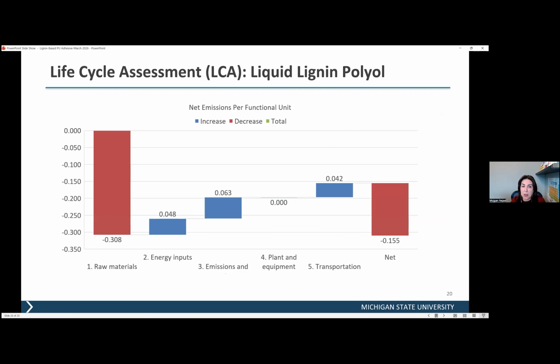We also hired an outside firm, and they did a life cycle assessment, LCA, for our liquid lignin polyol, which is the main component we are replacing with the petrochemical polyol. What they found is that, because we are using lignin that has bio-based carbon in it, we're going to end up having negative net zero carbon for our raw materials. We are using a little bit of energy, so there's going to be some small CO2 emission. The plants and equipment used show almost zero increase in CO2 emissions.